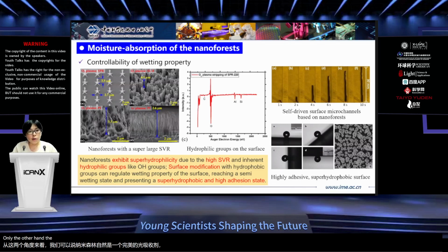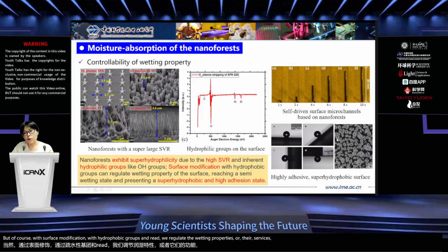On the other hand, the nanoforests also have a high moisture absorption property. As we can see here, the nanoforests have a super large surface to volume ratio. Besides, their inherent hydrophilic groups like hydroxyl groups make them super hydrophilic. Based on such nanoforest, self-driven surface microchannels with a relatively long driven distance can be formed. But of course, surface modification with hydrophobic groups can regulate the wetting properties of their surfaces, even to reach a semi-wetting state and to present a super hydrophobic and highly adhesive surface.